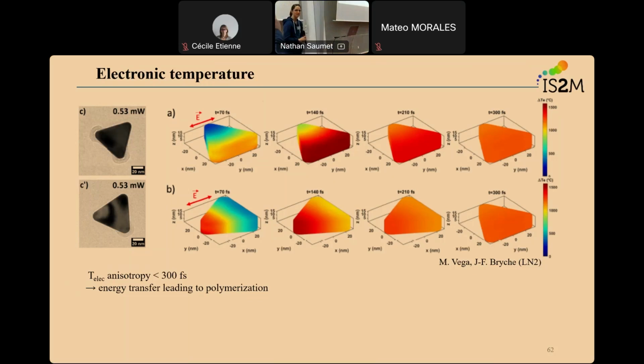I have a question concerning this slide as well. The extension we are observing on the image corresponds, in your opinion, to the electron-phonon coupling length or something more related to an electron mean free path? I mean, are electrons leaving the metallic environment and going to the polymer, or is it really phonons at this scale? I think it's more phonons because the media is outside the nanoparticle.